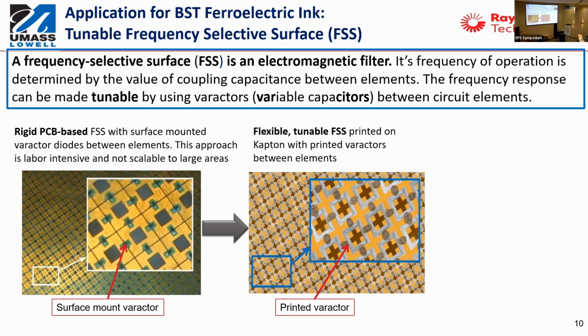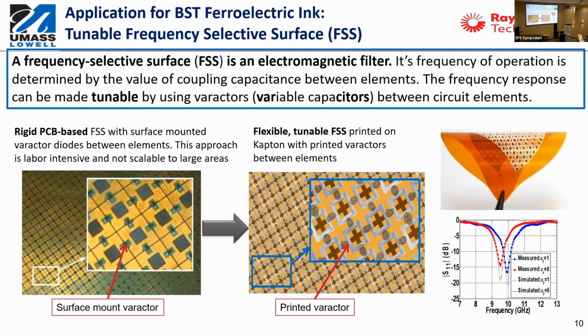What I'm pointing to with the arrow is a printed varactor, which is essentially a printed IDC, interdigitated capacitor, with the BST ink. So if you apply a bias to that ink, it changes the dielectric constant, and therefore it changes the capacitance. So here's a picture, and you might have seen this picture, anyone in the additive world. This picture is used a lot in different papers. You can see the dynamic tuning for this FSS structure using the BST-based varactor.